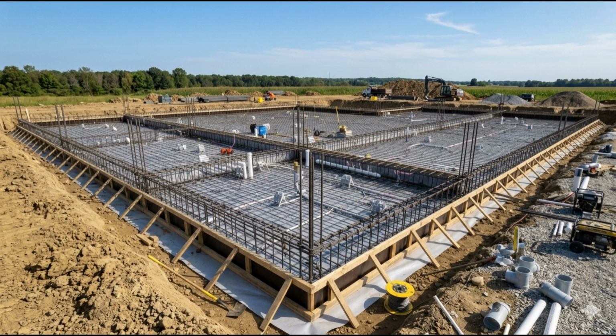This was the inspection he always conducted with the most care, because cracks in fresh concrete were common, and the question was never whether they existed but what they indicated and whether they required action. There were no structural cracks visible. There was a slight pattern of fine surface crazing, a network of very fine cracks no wider than a human hair, affecting only the top few millimeters of the slab surface, in one section near the east wall.